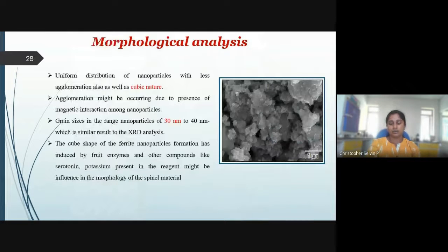Followed by the structural analysis, we went for morphological analysis by means of HRSEM. Morphological images of the zinc ferrite indicate cubic shaped grains. However, agglomeration of these grains is inevitable, which may be due to the involvement of the ferrite component in our sample. We calculated the grain size distribution using ImageJ software, which was in the range of 30 to 40 nanometer, which is also in line with the XRD results obtained earlier. The cube shape of the ferrite nanoparticles is induced by fruit enzymes and other compounds like serotonin and potassium present in the extract, which may influence the morphology of the spinel structure. This is highly commendable because it does not include any kind of artificial surfactants or capping agents.